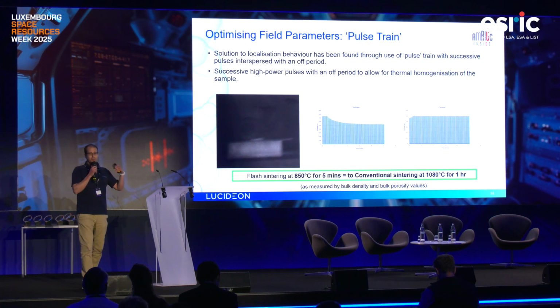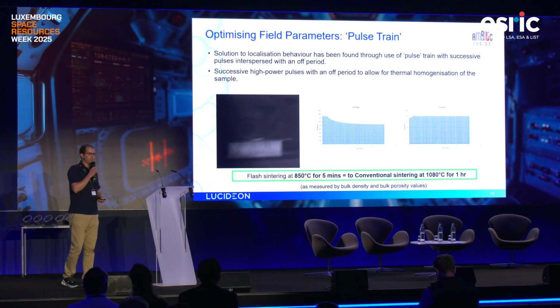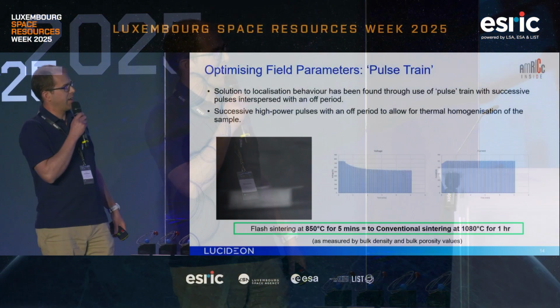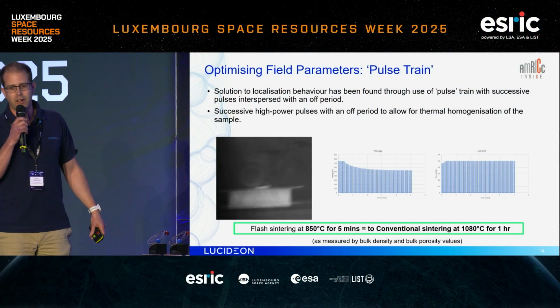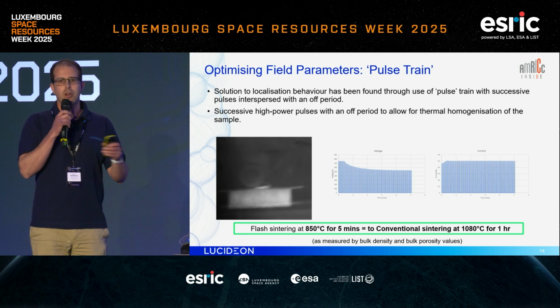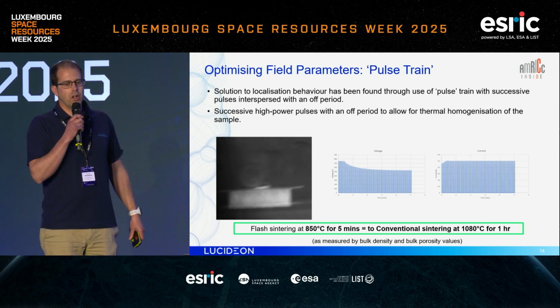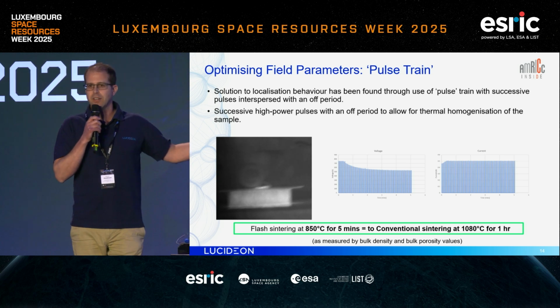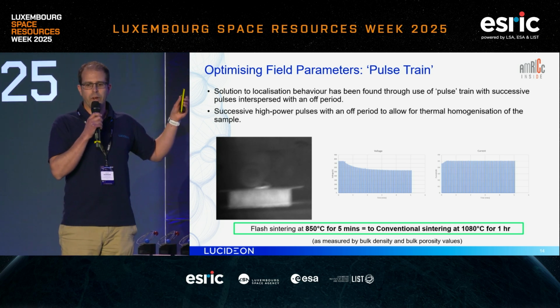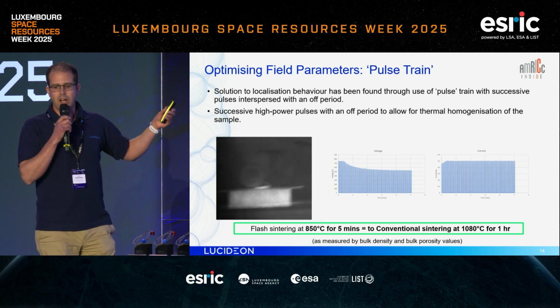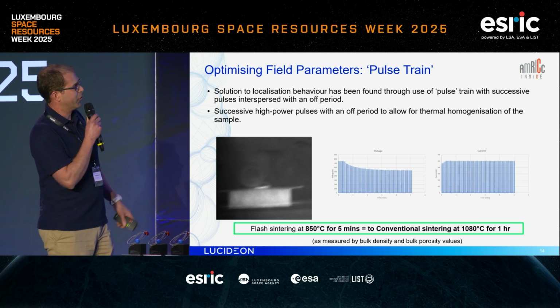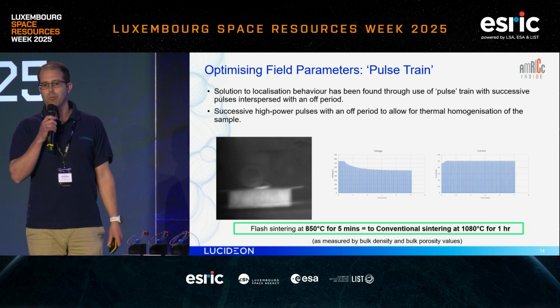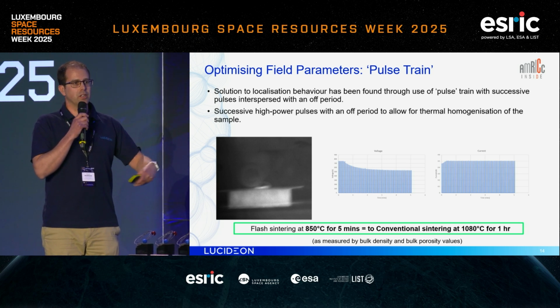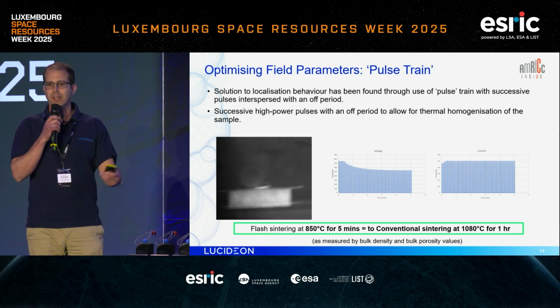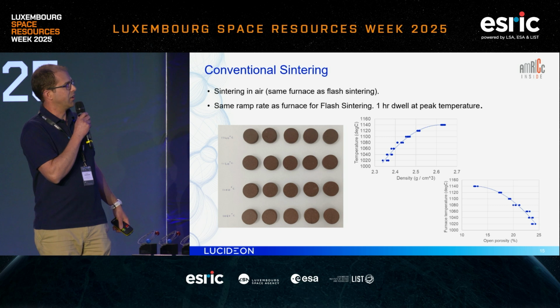So we've skipped forward quite a number of weeks and months' worth of work here as we optimize the field parameters for this. Okay, and the solution we came to, I'll play the video here, is essentially a pulse train where we are getting a high current pulse into the sample which thermally homogenizes as we go. So if we pulse these samples in an electric field for 5 minutes at a furnace temperature of 850 degrees, we can achieve the same as conventional sintering at 1080 for 1 hour. So we're really quite pleased with that, and we get a nice homogeneous sample throughout. And it's the way in which we overcame the local thermal runaways and managed to get some homogeneity.